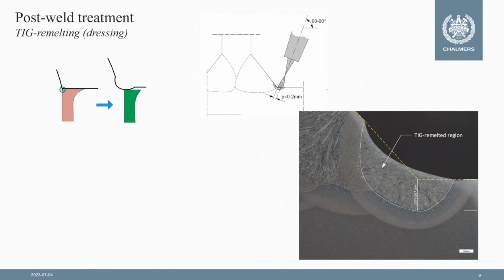The second method that should be mentioned here is to use TIG remelting or TIG dressing. The principle is to remelt the region at the weld toe in order to arrive at a smoother transition of the area where we would typically get toe cracking. By doing so, we also get a better fatigue performance, typically one to two detail categories better than the as-welded condition. So these are two, let's say, traditional methods that have been applied before.